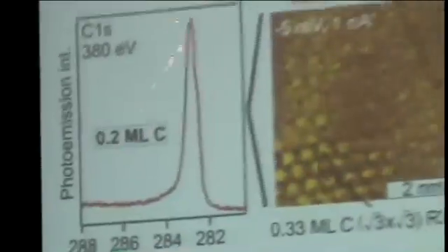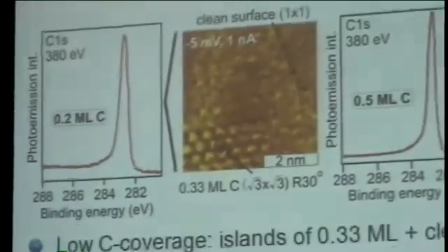If we put a small amount of atomic carbon on the surface, we don't see any surface rearrangement of the cobalt. What we in fact find is that these carbon atoms cluster together, they make small islands with a local high density, and they're surrounded just by empty cobalt. And you can deduce that just from the periodicity of the lattice distance, which you can measure with STM.